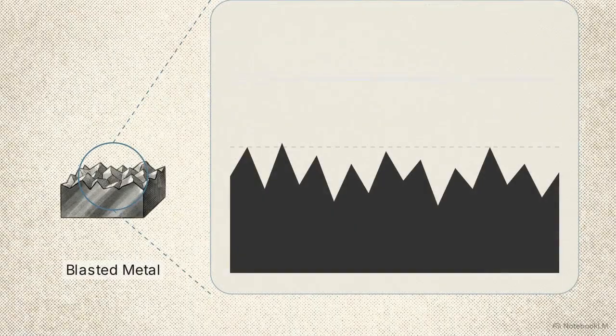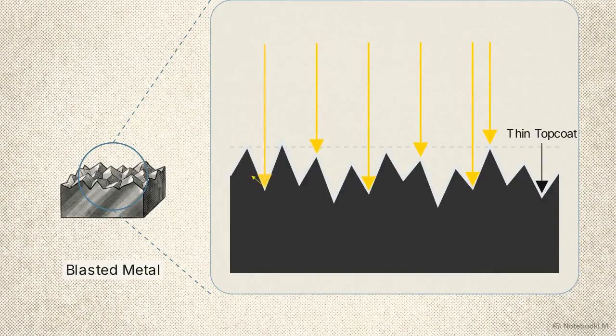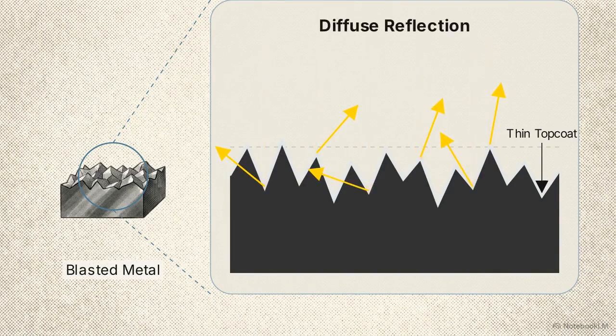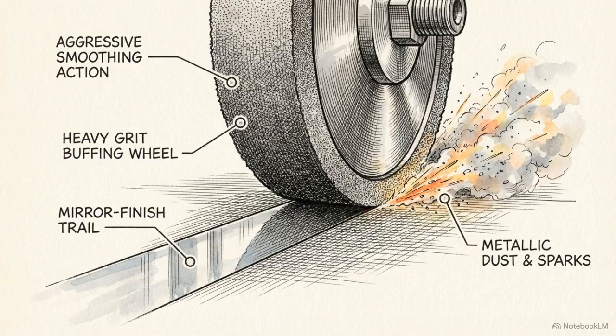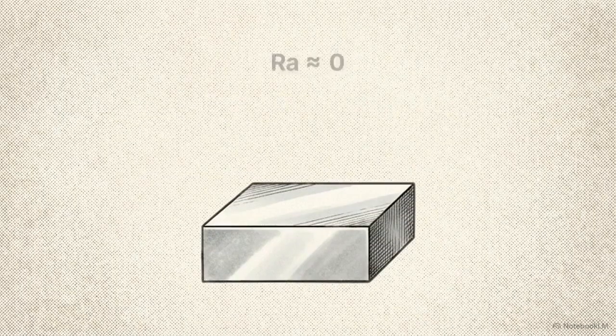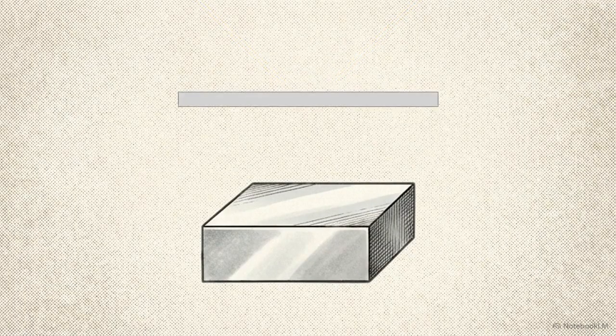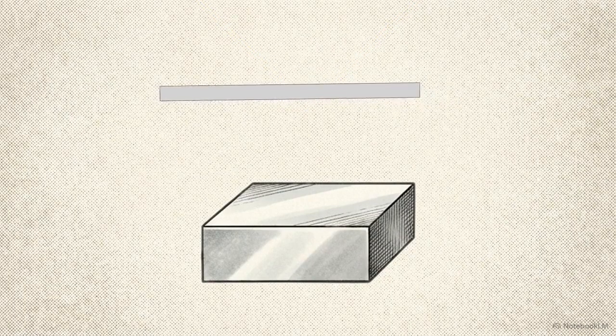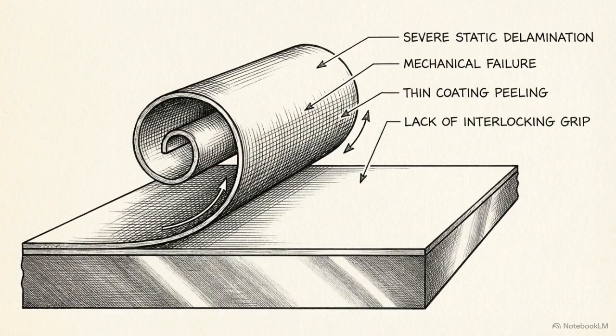Decorative layers are thin, meaning the jagged topography of the blasted metal translates completely through the top coat, scattering light and dulling the final appearance. The alternative mechanical method is polishing. Instead of gouging the metal, polishing aggressively smooths the surface down to a mirror-like baseline. Polishing drops the Ra value effectively to 0, solving the light scattering problem, but doing so eliminates the mechanical anchoring sites. Purely mechanical approaches hit a dead end here.